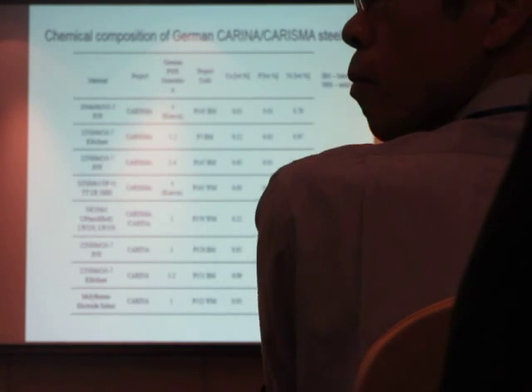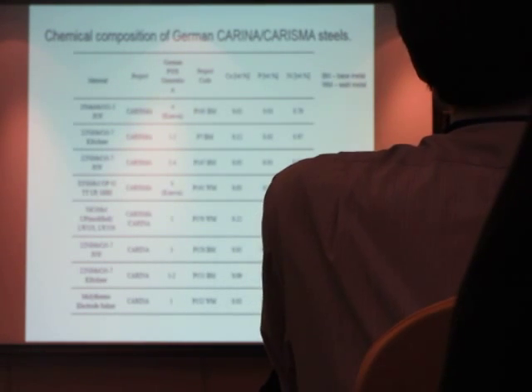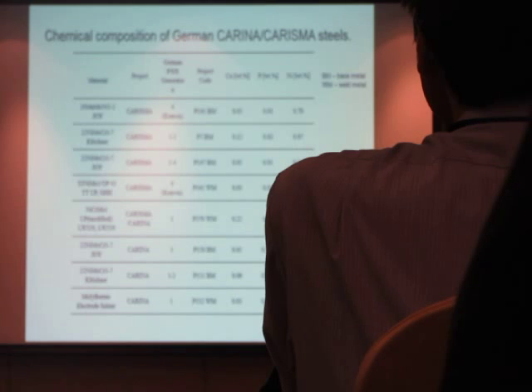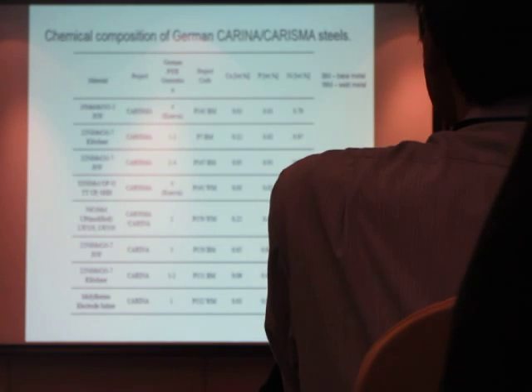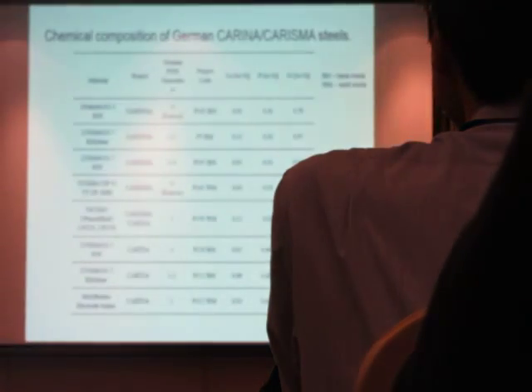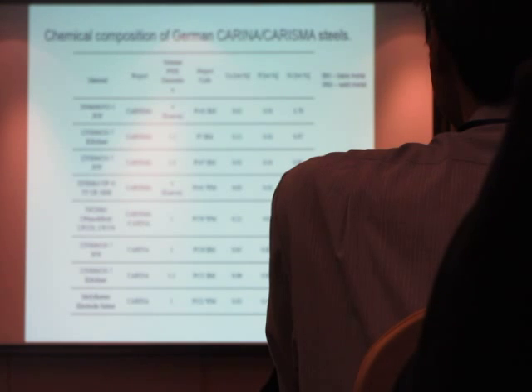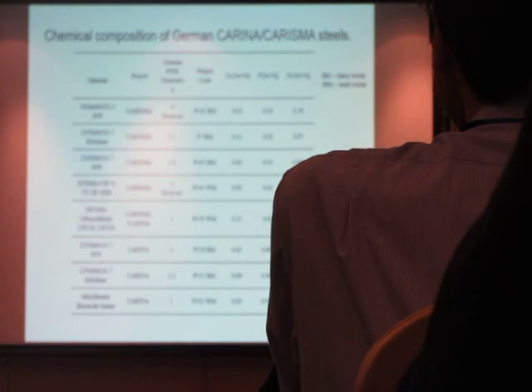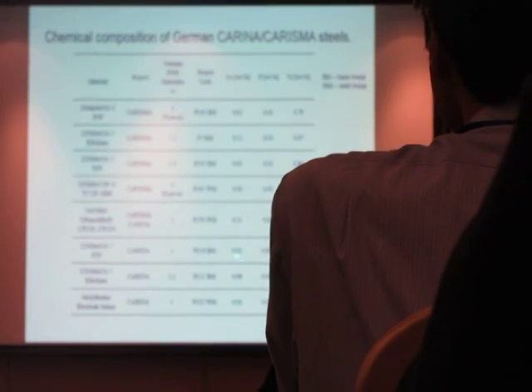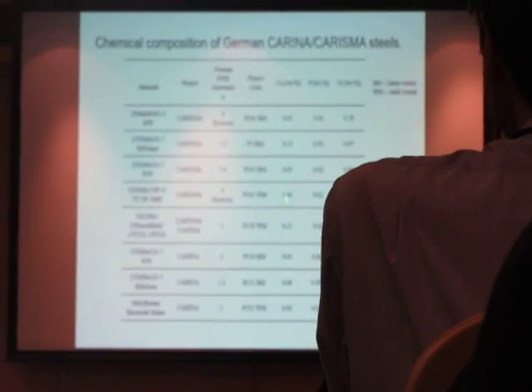So for the German steels, we were lucky because in Germany different generations of the steels were put in the reactor in the 80s, and after several years of irradiation were taken out and studied 30 years ago. So the cobalt-60 activity was substantial. You can see different levels of the alloying elements. Most important is copper, because about copper precipitation we can speak for a long time.